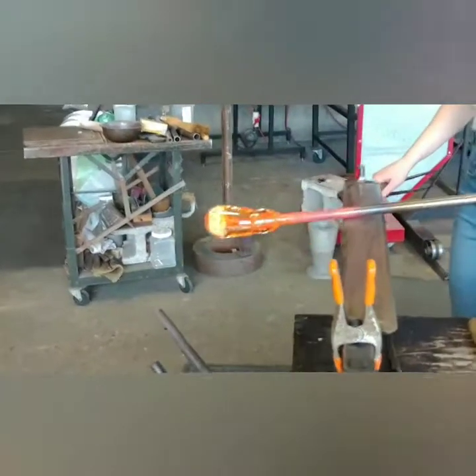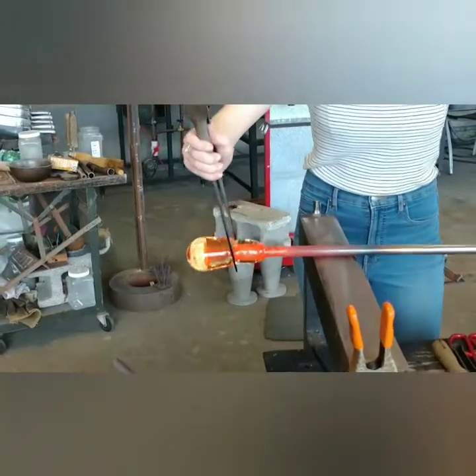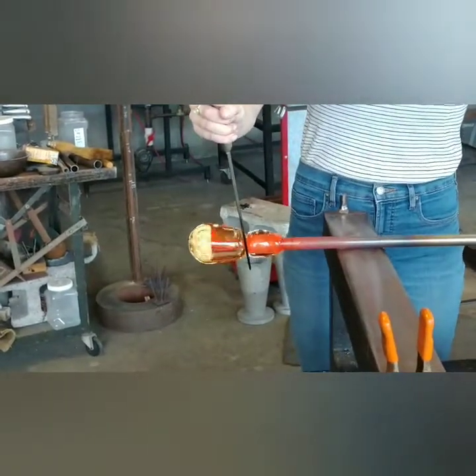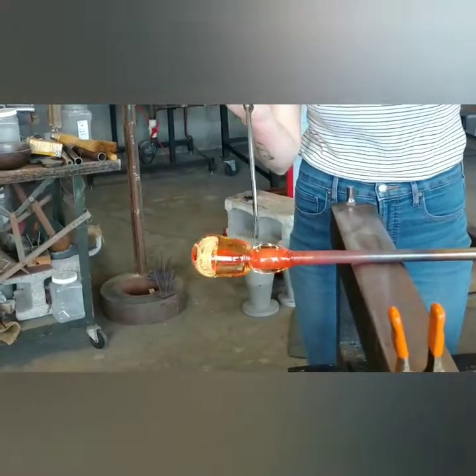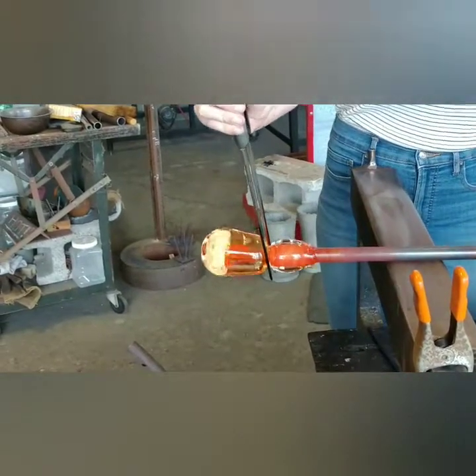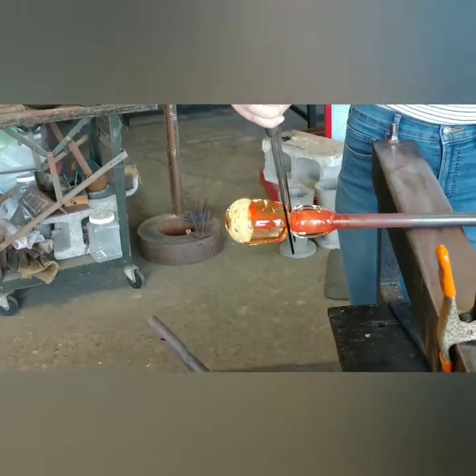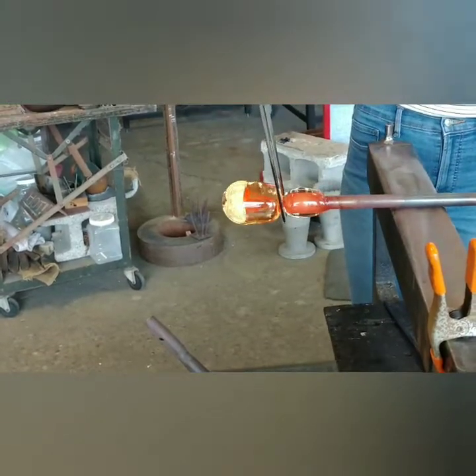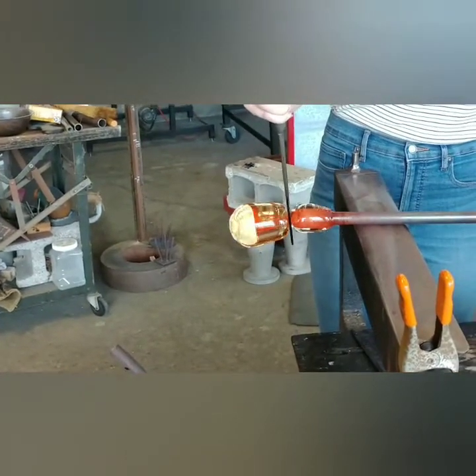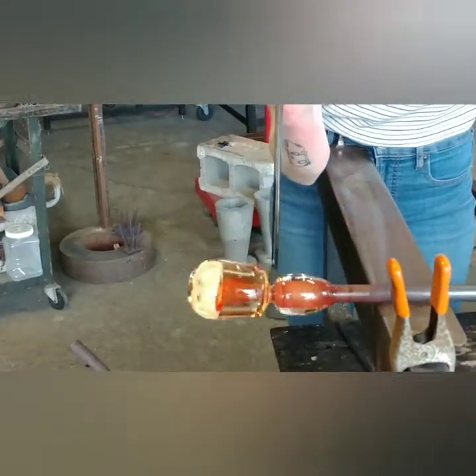You can see that the red already looks quite a bit darker while hot, but once it cools back down to room temperature it's going to look totally different. It's starting to cut in this line. I don't want to squeeze down too hard because it'll get out of hand. The glass is moving a lot and I'm turning pretty quickly — I want to be turning faster than I'm squeezing in. If the glass is too cold, we can't really change anything, so we'll bring it back up to temperature so we can make each of the changes throughout the process. Now I've got a good constriction line and the glass will know exactly where to break.